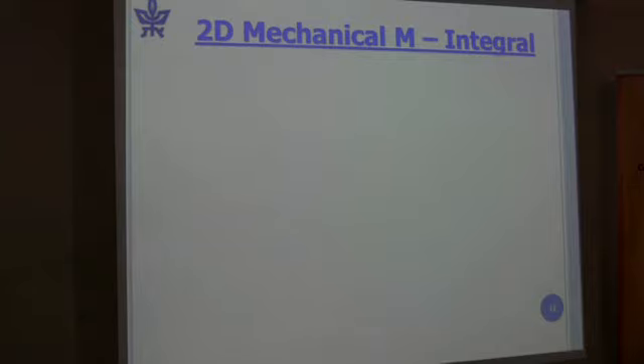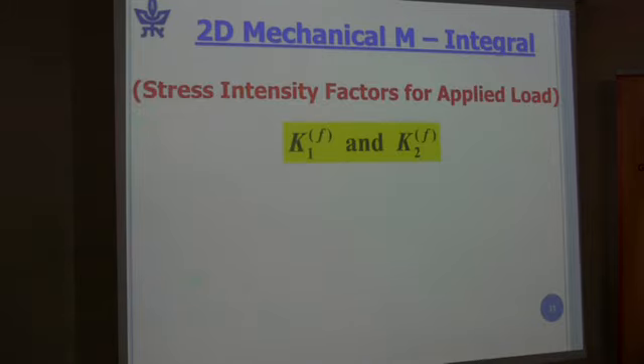And so now we needed to analyze our test specimens. We carried out a test, we obtained the applied load, we know the geometry, we know the crack length, the delamination length when it fractures. And so we used finite elements and a conservative M integral, and we only did this in 2 dimensions, and we examined the implications of that, and it's okay. And so we obtained K1 for applied load and K2 for applied load. One mustn't forget that when you have composite materials, you're curing them.